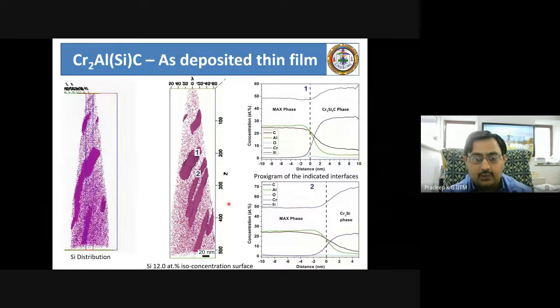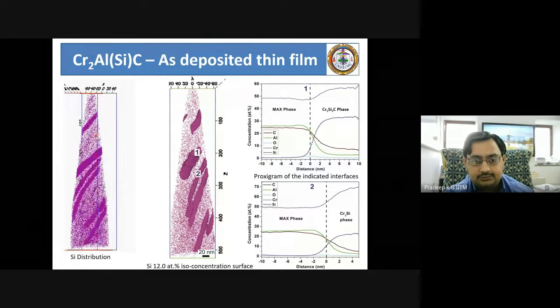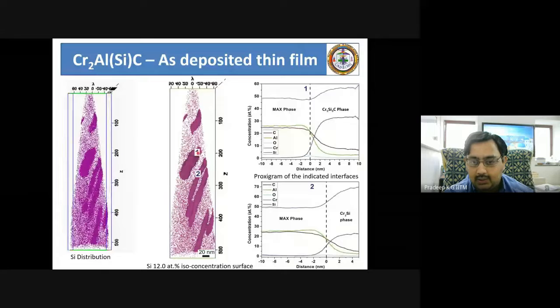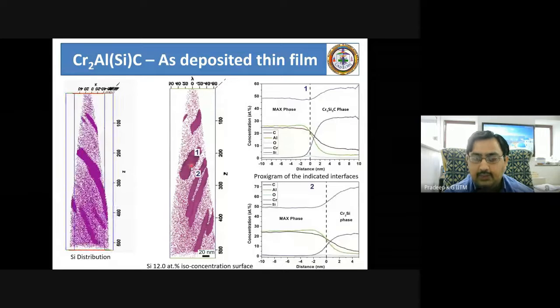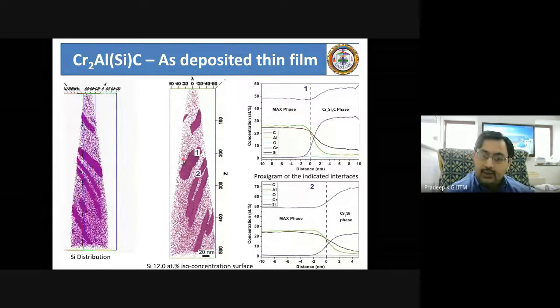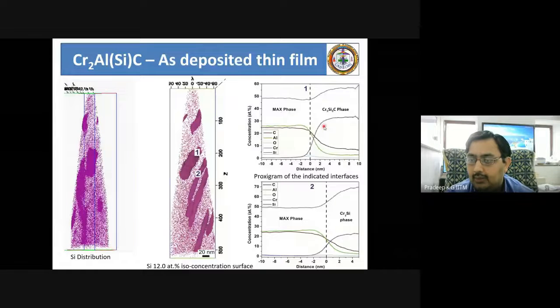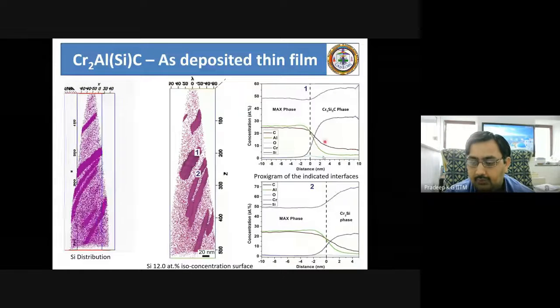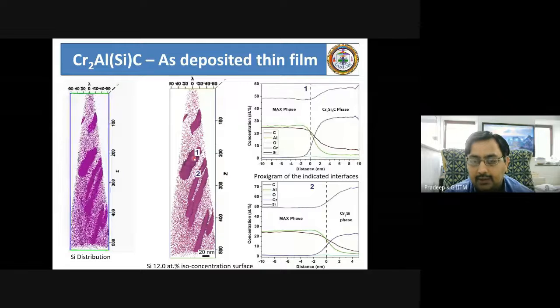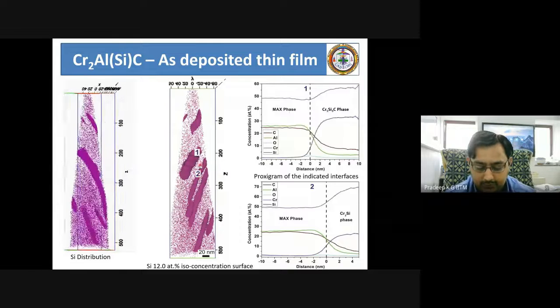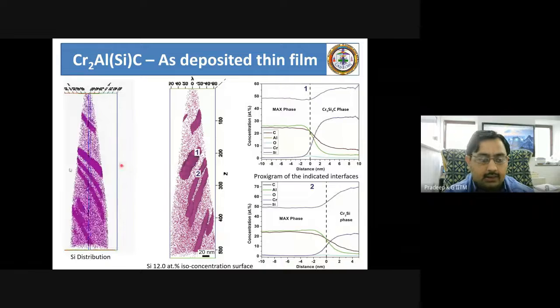So now one can realize that at the atomic scale, there are a lot more things that are happening, and even in the nanometer scale, you have a completely different chemical constitution of a phase, but they are distinctly visualized as 1 and 2 using this atom probe tomography, which was not possible by other methods as what you have seen before.